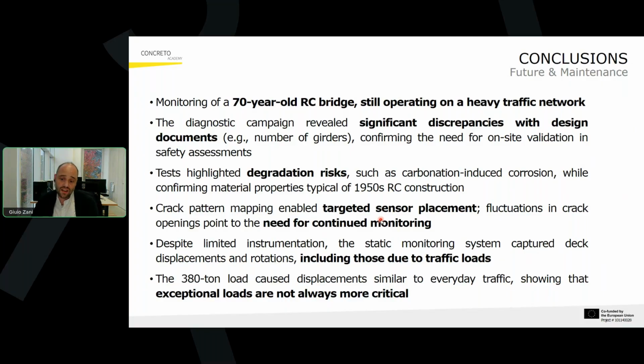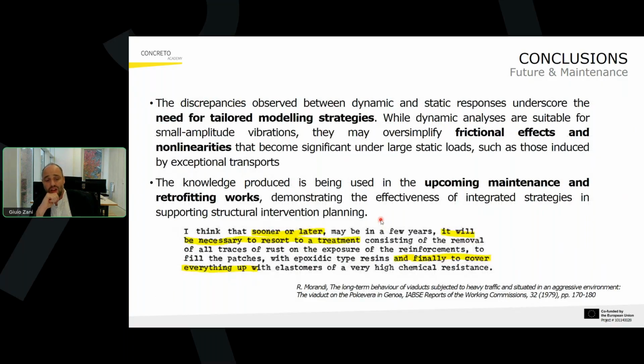And also the load test showed that exceptional loads are not always more critical than ordinary traffic conditions. We also found some discrepancies, so please be aware that optimizing and tuning the numerical model on ambient vibration tests is sometimes not enough, because it's always important also to have a static load test to understand whether the modeling